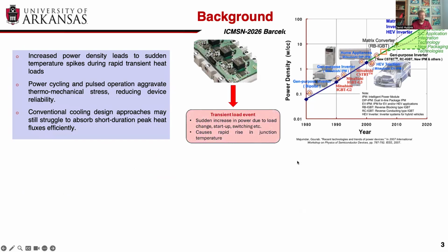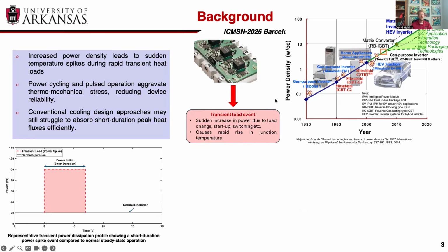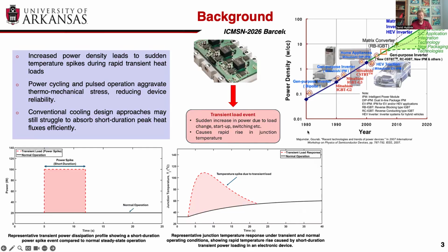And when we talk about EV power systems, like you see in power electronics, there are a lot of transient load events that you can encounter. You can imagine trying to accelerate away from a stoplight, that there is a sudden burst of energy that has to be dealt with in the electronics. And that power spike leads to a very rapid temperature rise in the electronic devices themselves, which can contribute dramatically